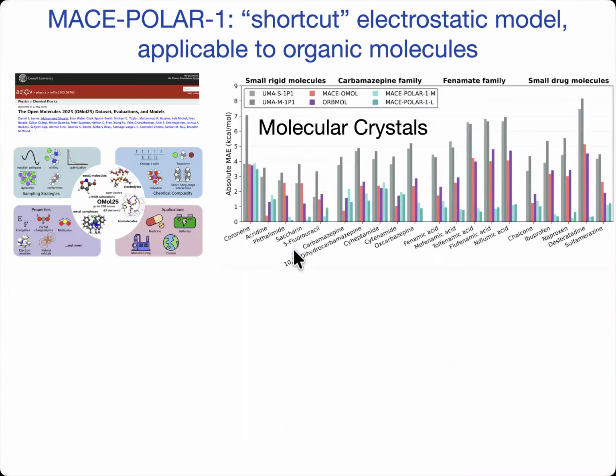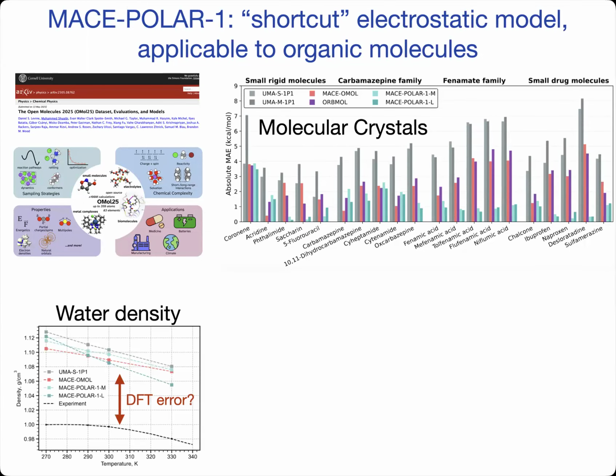And when you do this, things on this OMol type fit, and you test it on difficult problems, things dramatically improve. So for molecular crystals, this is now a much larger set of crystals than what I've shown before, and you see these cyan colors are the two different versions, medium and large, of this polarizable model. And the other models are also trained on OMol, but don't have explicit electrostatics in them, and you get a dramatic improvement.